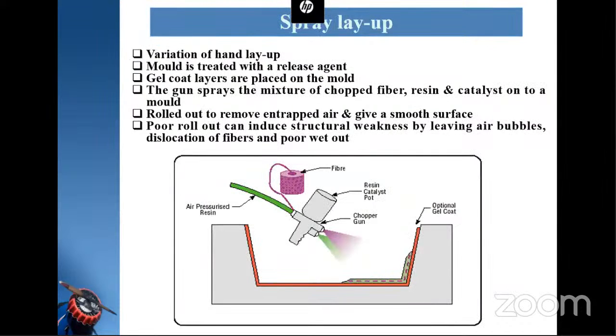Just like the hand layup process, there is another technique called the spray layup process, which is used for commercial applications and mass production. Here the fiber and resin are both cut and sprayed by using a gun. This layup process also uses a one-side mold. It is a variation of the hand layup technique. The mold is treated with release agent. Gel coat layers are placed on the mold. The gun sprays the mixture of chopped fiber, resin and a catalyst onto the mold. It is rolled out to remove entrapped air and give a smooth surface. Poor rollout can induce structural weakness by leaving air bubbles, dislocation of fibers, and poor wet out.